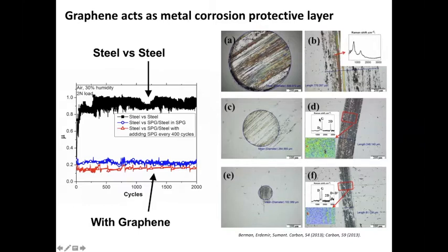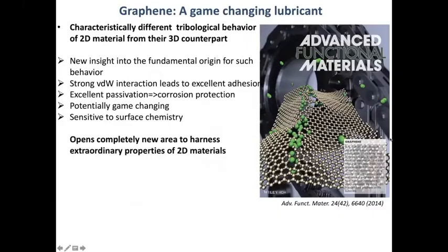So here you can see the Raman signature inside the wear track. It has a very uniform distribution for the 2D peak and the G peak inside the wear track. And why is this happening? Because of the smoothening of the graphene layers, providing this more uniform protection. The interesting thing in all of this was that graphene really demonstrated the ability to work well across different environments. We can further extend its life by adding, for example, hydrogen gas or improving the overlaying of the graphene flakes, and then also replenishing the graphene coating by adding a graphene-based solution on the surfaces.